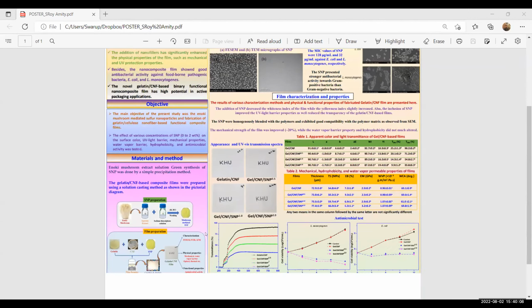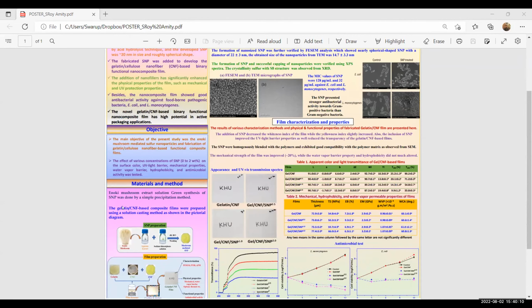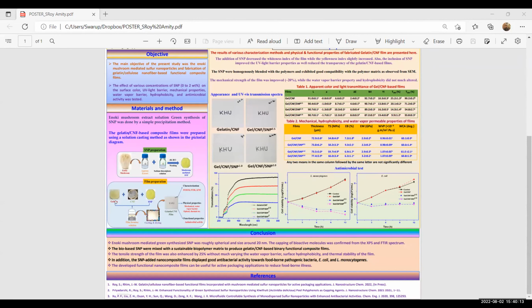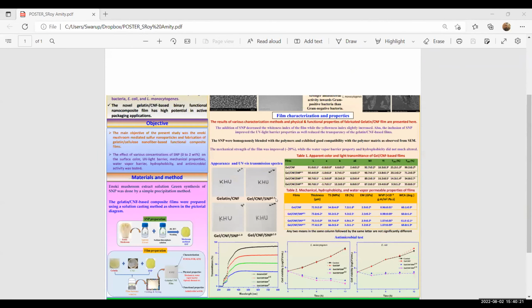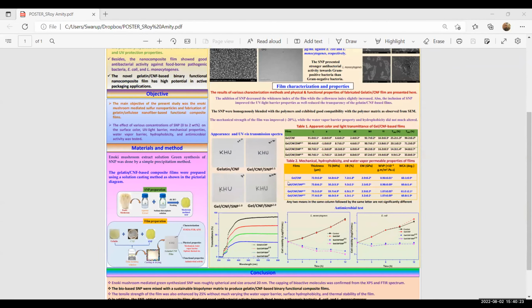So this nanoparticle was used to fabricate the film. This is the schematic diagram. Gelatin, cellulose nanofiber, and sulfur nanoparticles are combined to produce a packaging film using the solution casting method. Among various film properties studied, this is the apparent appearance of the film. Three different concentrations of sulfur nanoparticles are used: 0.5, 1, and 2%. It is observed that by adding the sulfur nanoparticle, the color of the film becomes yellowish, as indicated from the increase in b value.